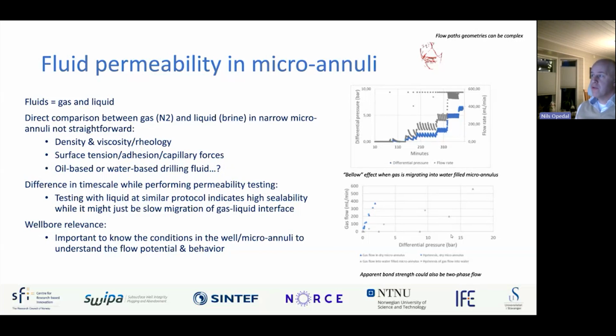The case if you have, for instance, a dry microannulus and you flow gas through it is pretty straightforward. But if you have, for instance, a submerged sample with the microannulus filled with water and you apply gas through it, the behavior is sometimes a little bit more difficult to understand. The figure on the right-hand side shows gas being tested through a microannulus, and it doesn't really stabilize when you have a differential pressure. The measured flow rate doesn't stabilize, a seemingly bellows effect when the gas is migrating through a water-filled microannulus.